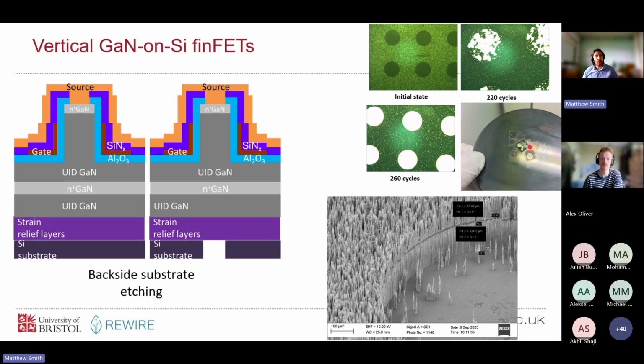The challenge is, when I've made these types of structures in the past, you can maybe kind of see it here. The gallium nitride, the nitride membrane that's left behind when you etch, is quite high stress, so it's bowed like this. So controlling that can be quite challenging. And actually, maybe a major drawback is going to be thermal effects. So how do we handle the large amounts of heat that are associated with the high currents that we get as we're passing things vertically? There are ways that can be managed, certainly lots of ideas, things to try, but I know that's a concern that, when these sort of membrane devices were explored a few years ago, was a big limitation that they came across.